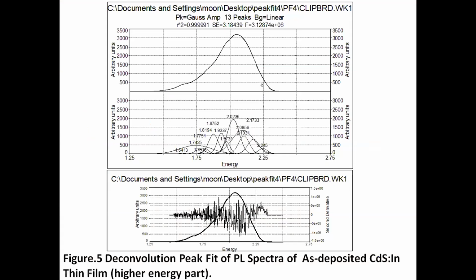Now a deconvolution peak fit was performed for the peak in the yellow region, which covers the red and yellow bands, and the spectrum is fitted to Gaussian peaks. We get 13 peaks after the fit. Now the positions of the peaks are confirmed by evaluating the second derivative, where, as you know, the position of the peak is at the minima of the second derivative. Now we see here the center of the yellow band is at 2.0236 electron volt.